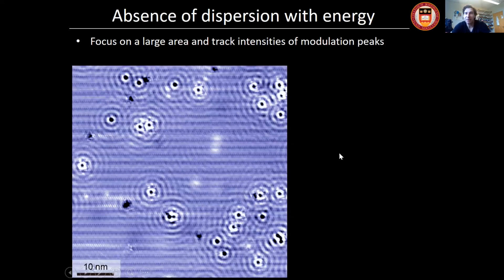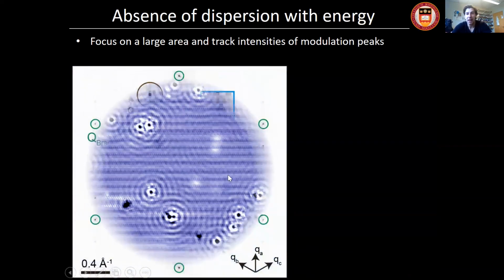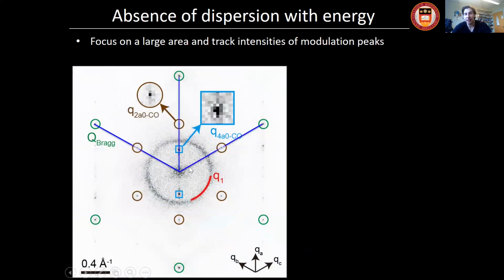So we wanted to investigate it in a little more detail. We focused on a large area to get a nice k-space resolution, right? The larger the real space area, the better the Q-space resolution is. And then we took line cuts along different atomic Bragg peak directions. There are 3 different lattice directions, and we investigated the fate of these wave vectors as a function of energy. So that's the first taste of any charge ordering, at least from STM.